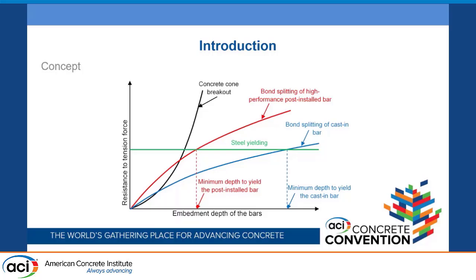When we talk about cast-in anchorages, we do not consider concrete cone breakout as a possible failure mode. We take the bond splitting of the cast-in rebars, and then steel yielding. If your development length is enough, which is beyond this point, you will get steel yielding. When we talk about bonded anchors, we do not consider the same kind of splitting model. It's a different kind of splitting model, and we have concrete cone breakout, steel yielding, and some other failure modes.